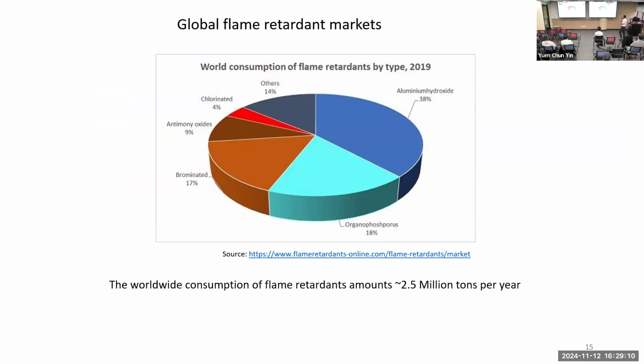If you look at the different kinds of flame retardants, organic and inorganic, the world is dominated by inorganic flame retardants, okay? And they are cheap. You can see the oxides are quite cheap and quite effective as well. But you need a lot of these additives. For example, in cable, you need up to 50% of aluminum hydroxide or magnesium hydroxide to make the whole system flame retardant. But then you have the organic flame retardants. These are like the halogenated ones, which probably are problematic. They have to be replaced at one point. But then you also have organophosphorus ones, or phosphorus-based flame retardants, which are considered to be a good compromise between toxicity, performance, and price. Okay, it doesn't mean that they are all good. You just have to look and see which of them meets your requirement.